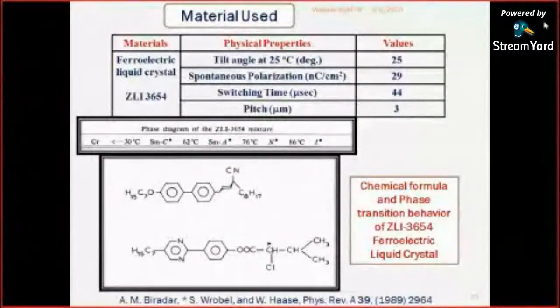After cooling it, we again investigate its morphological properties by using the optical microscope, or the polarizing optical microscope. So these are the materials used to investigate liquid crystal properties. Here we have used a ferroelectric liquid crystal material, which has tilt angle 25 degrees, spontaneous polarization 29 nanocoulomb per square centimeter, and the switching response is 44 microseconds. Again, the pitch is 3 micrometer, and this sample shows different phases: smectic C star phase at minus 30 degrees Celsius, smectic A star phase at 62 degrees Celsius, and chiral nematic phase at 76 degrees Celsius.